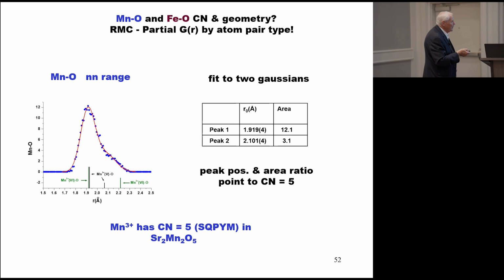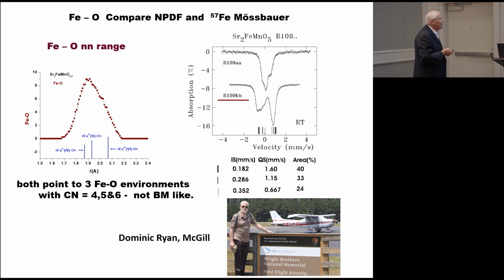and that is consistent with square pyramidal coordination, not octahedral coordination. And interestingly, of course, for manganese 3+, there's another phase which is not a Brownmillerite, strontium 2, manganese 2, oxygen 5. And in this phase, manganese does in fact have a 5-fold coordination. The iron case is also interesting. It should be tetrahedral, 4-fold coordination.